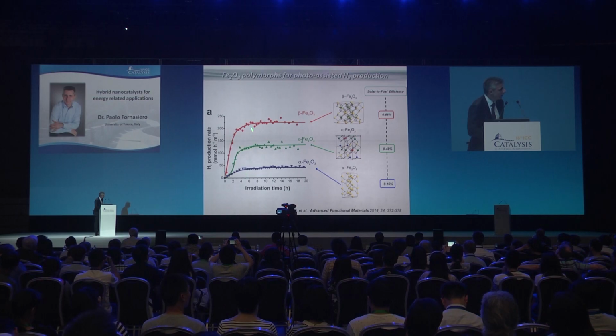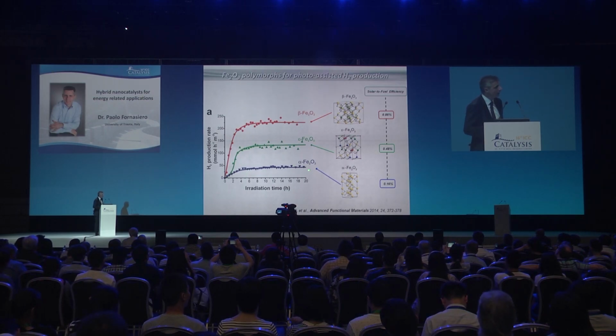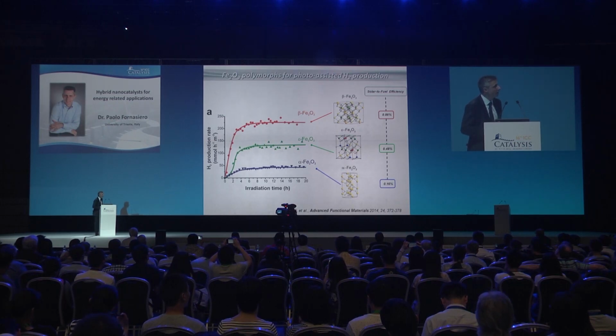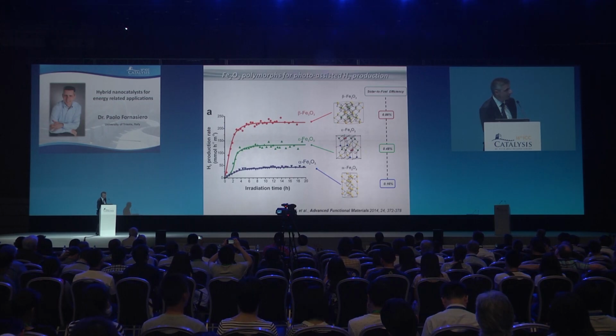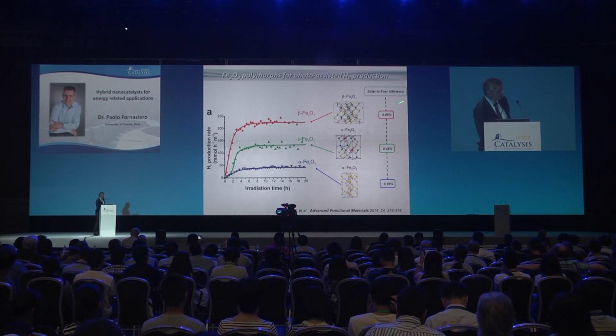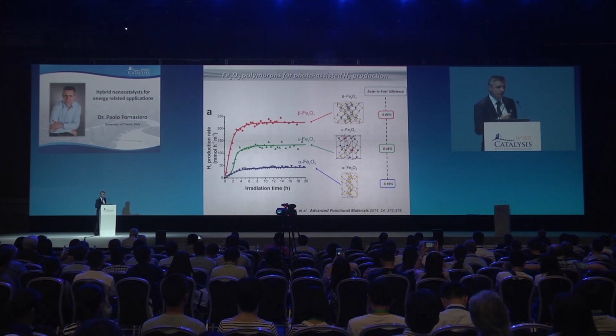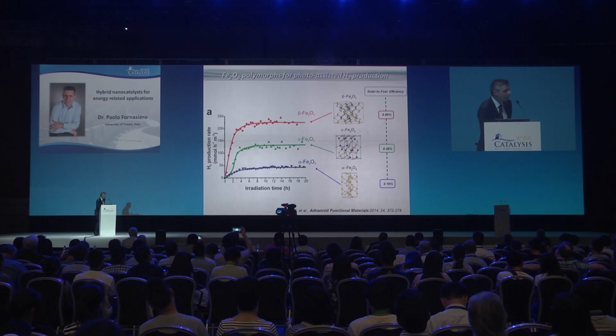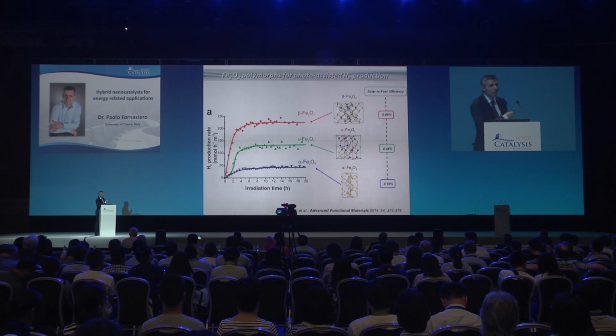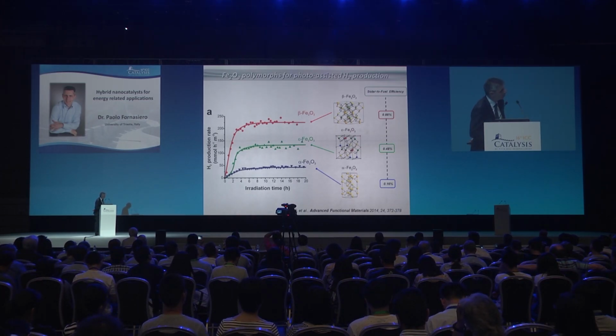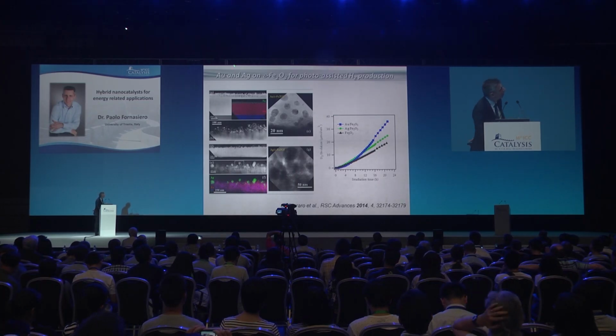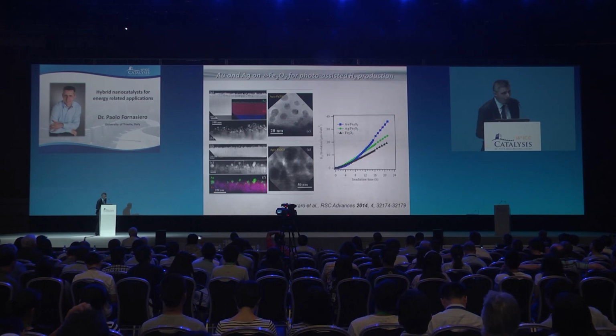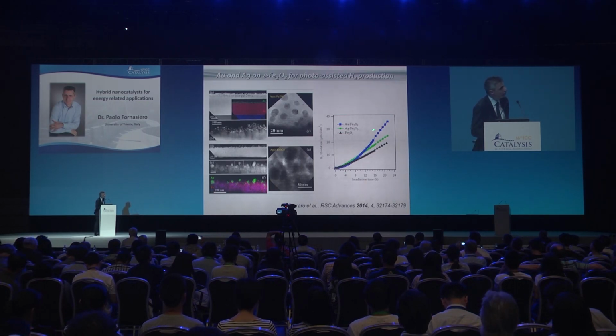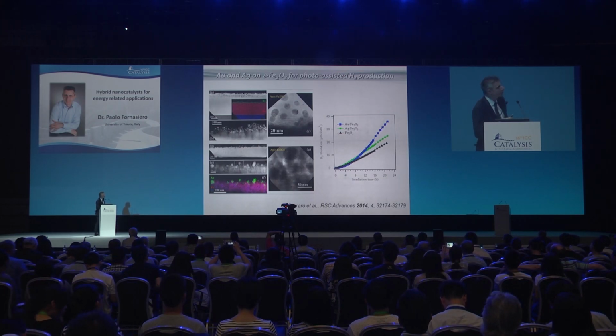Right after an initial induction period, you get bubbles of hydrogen. And the amount of hydrogen strongly depends on the type of polymorph, as well as the stability. In the case of hematite, you have leaching of iron in solution. The solar-to-fuel efficiency is quite low, but this is just a proof of concept that you can get hydrogen with this type of material. Of course, you can cheat and get a quantum efficiency of about 20% if you use UV light at the right excitation. You can also add plasmonic gold or silver, and you can increase the amount of hydrogen you get even in pure visible light.